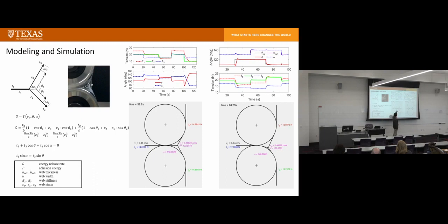You have to define the speed, you have to define the angle, and then find where it is because it's in the planar 2D surface. So we developed this model, and the model works very well. Since we know that when we change tensions, we can change the peeling angle, reversely, if we develop a reverse model, right? We can invert the model. The model will give us, in any case, what we need if we want to control the peeling angle.